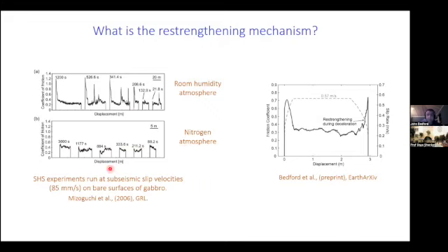So one thing I tried to do was actually perform similar bare surface experiments, but at higher slip velocities, the same slip velocities I performed in the gouge, to see if we get a change in the healing rate, and to compare to the study of Mizoguchi. But what we found is that actually during bare surface experiments, where the deformation is much more localized than it is during the gouge experiments, the restrengthening actually occurs during the deceleration phase of the experiment itself. It doesn't occur once slip has stopped like it does for the gouge experiments. So at higher slip velocity on bare surfaces, the healing mechanisms, whatever they are, are operating so fast that we get restrengthening during deceleration itself.